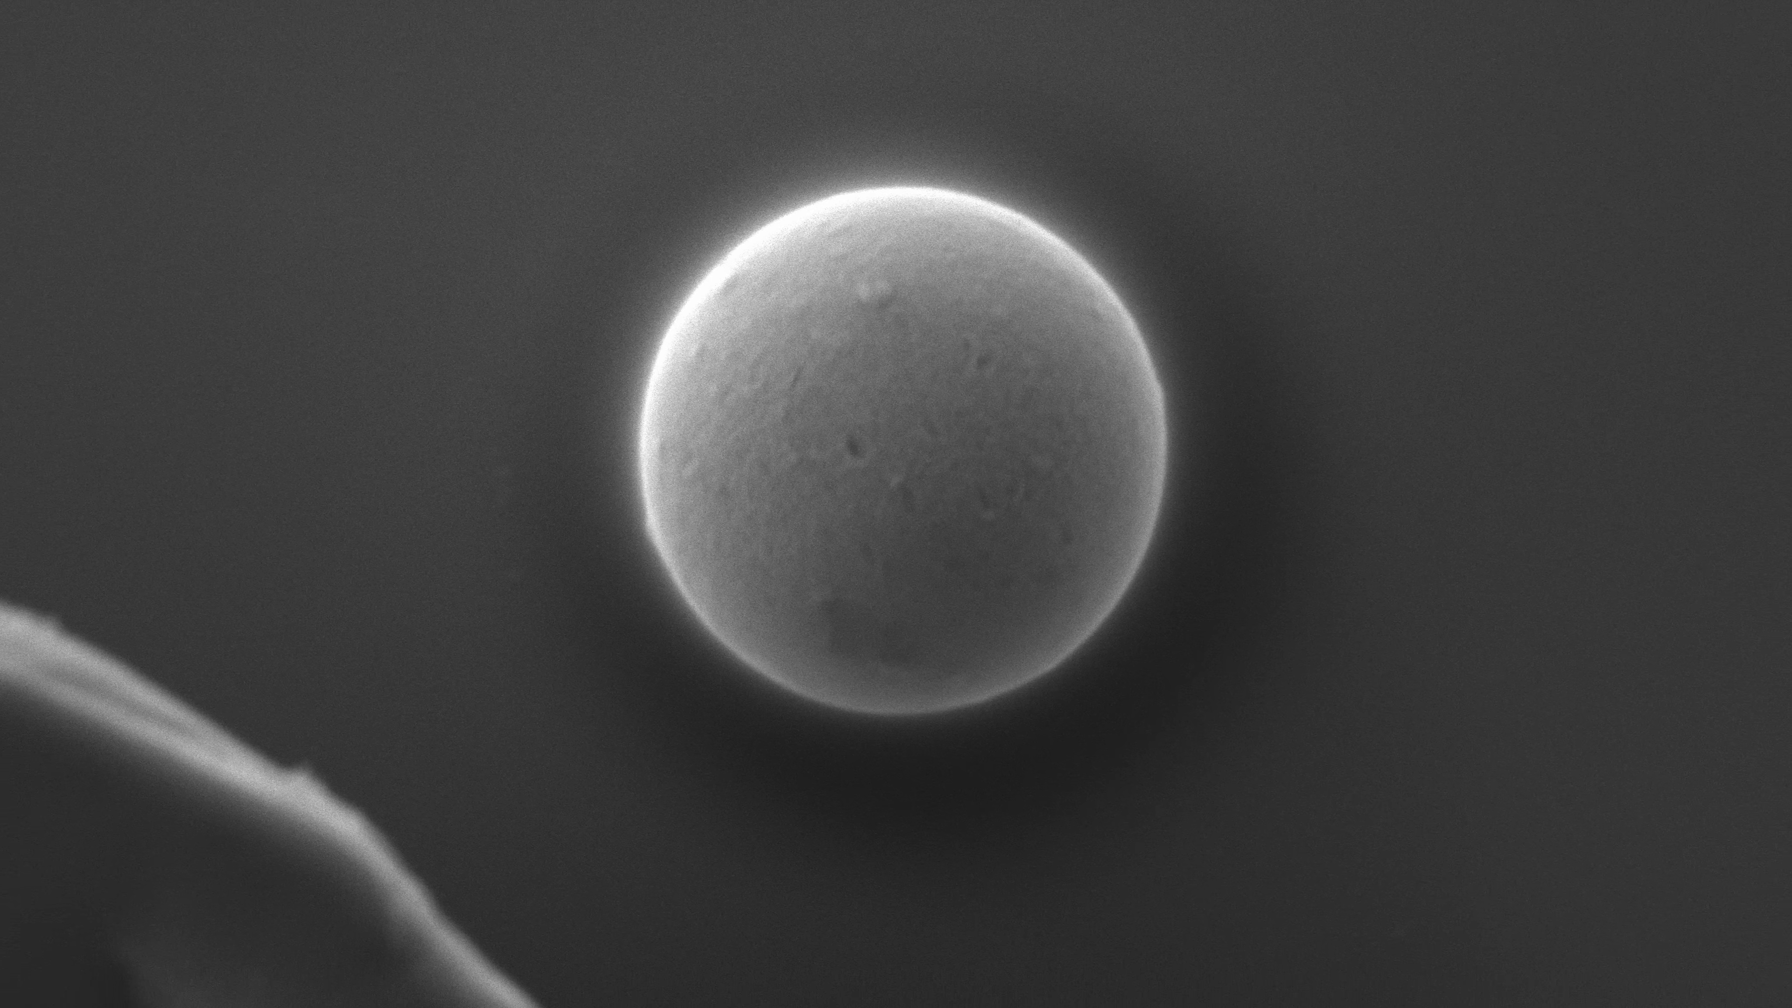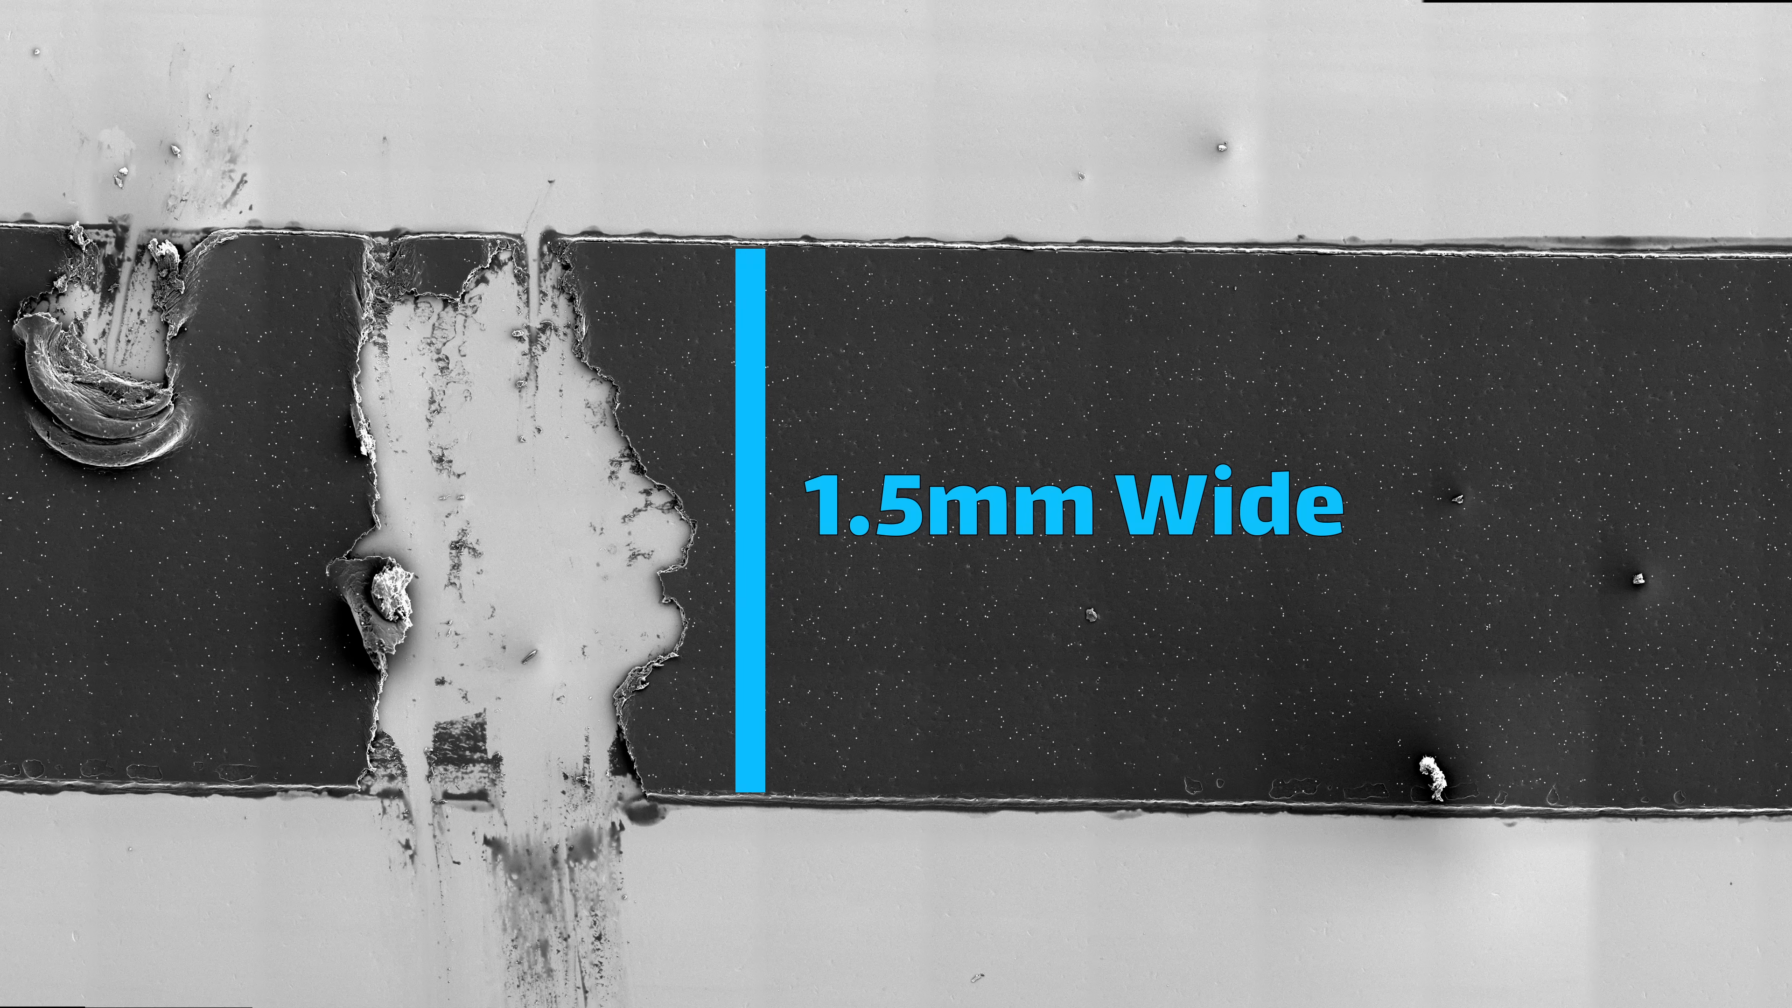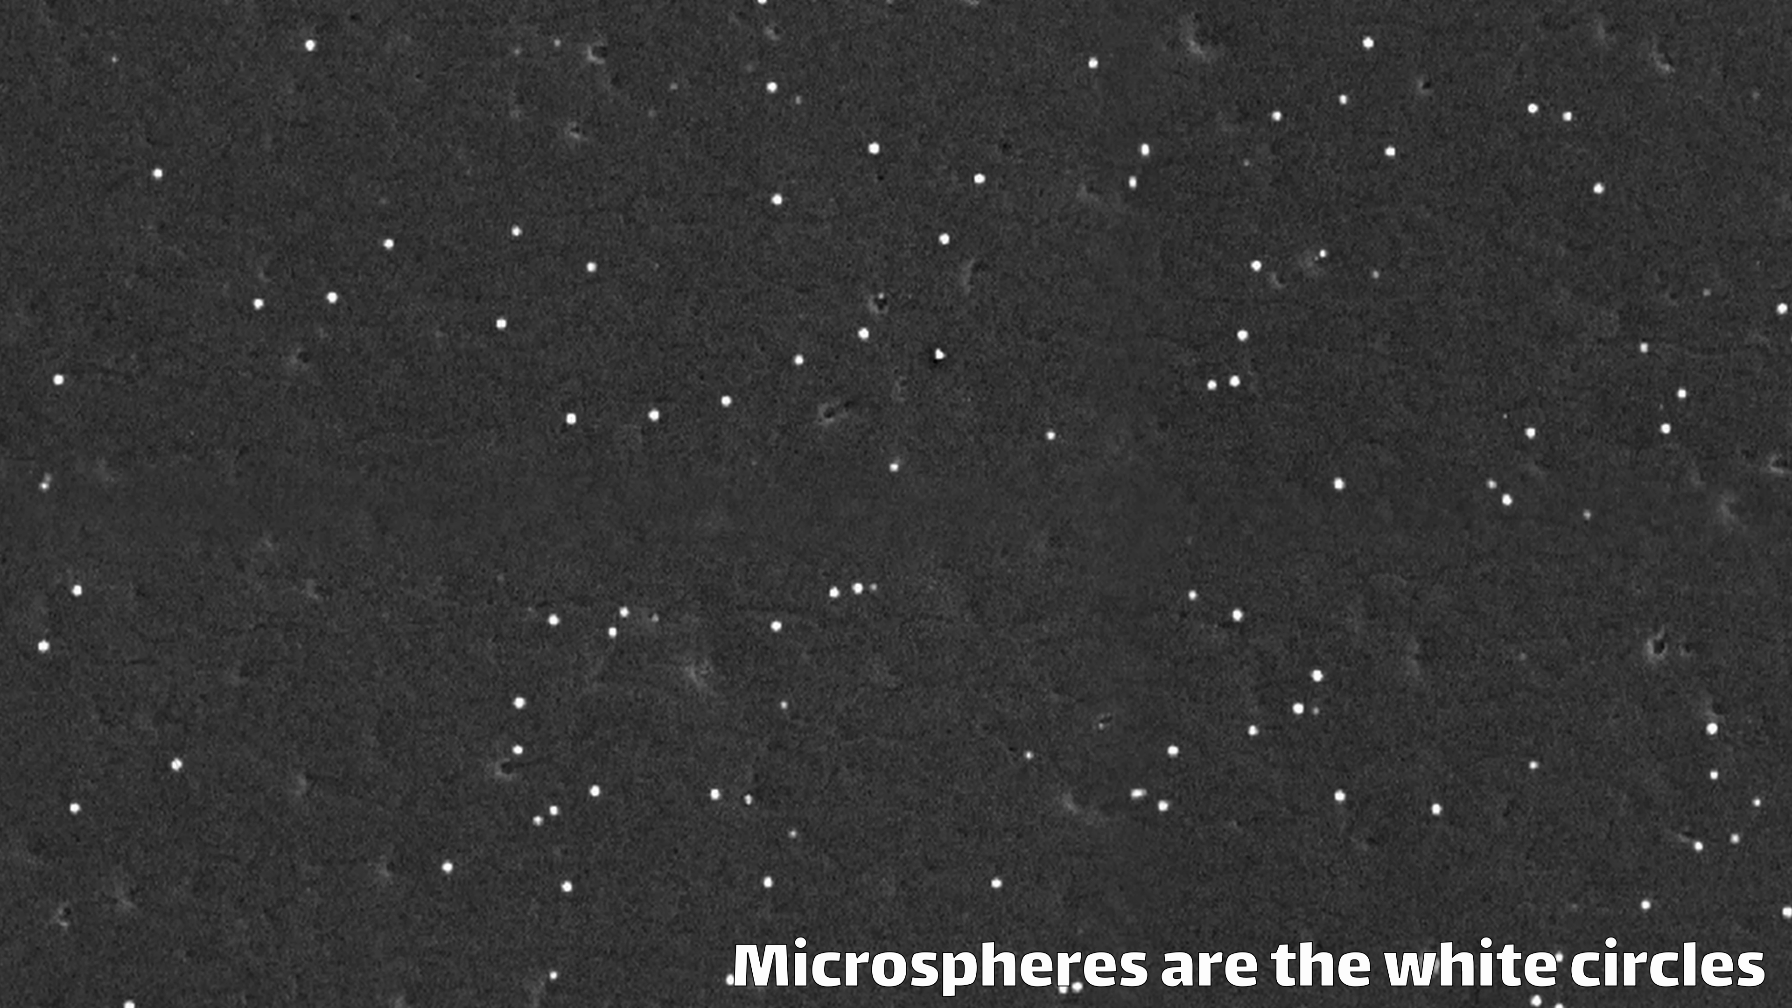So Real ACF uses plastic microspheres, which are coated in a thin film of metal. My tape has spheres which are about 3-5 micrometers wide and are coated in gold and nickel. You can see the spheres are randomly distributed throughout the film and are actually pretty sparse, which surprised me to a degree. But it makes sense because we want just enough microspheres for them to bridge the pads, but not so many that we accidentally build a bridge between the two adjacent pads.